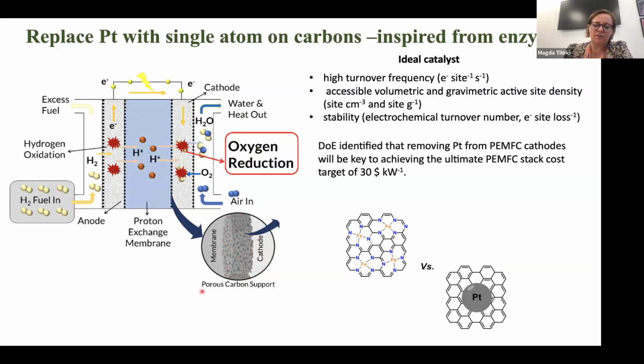And the way it works is you have a membrane electrode assembly where you have your carbon support, normally with some platinum nanoparticles, and the membrane. So you have a lot of interfaces here between the membrane and your active electrode, between your catalyst layer and the carbon support. And also because you have liquid, solid, and gas, you have even more complex interfaces. Now, as I said, normally for fuel cells to catalyze this oxygen reduction reaction, you use platinum on carbon. But very popular to replace the use of platinum, which is also very expensive, like it is iridium oxide for electrolyzers, you have the opportunity to do this single atom catalyst, which is basically a molecular catalyst, which is one iron atom coordinated to 4 nitrogens supported on a conductive carbon.